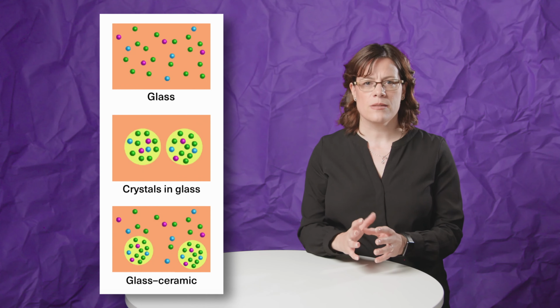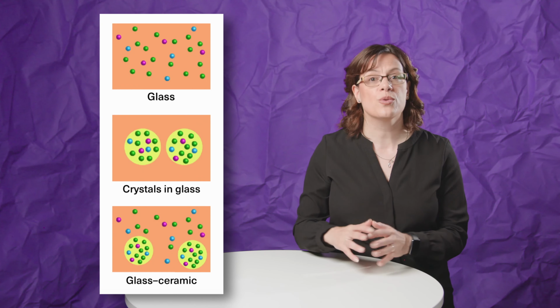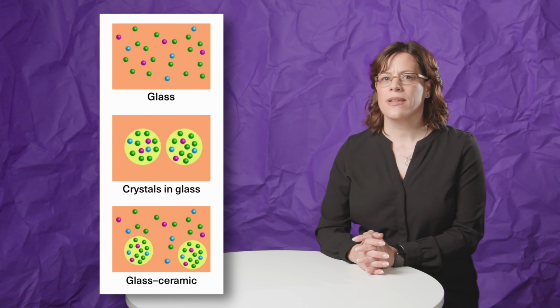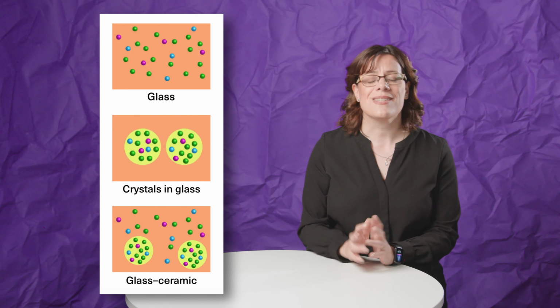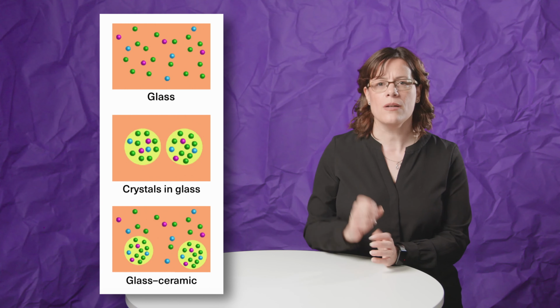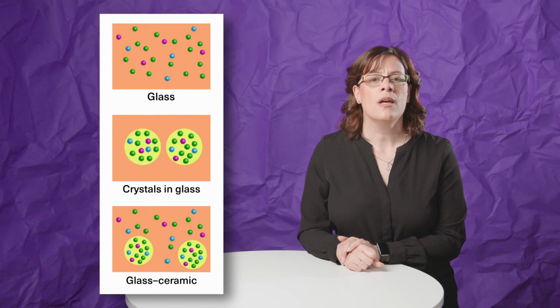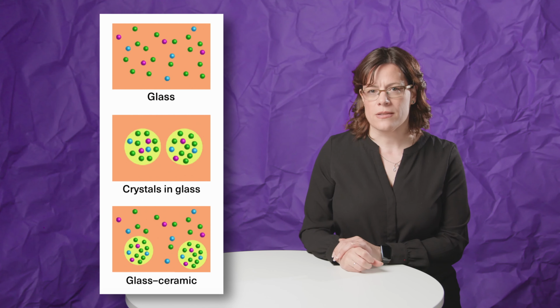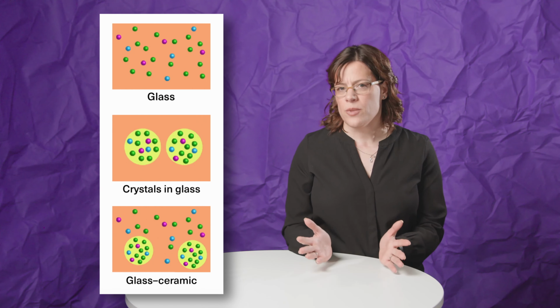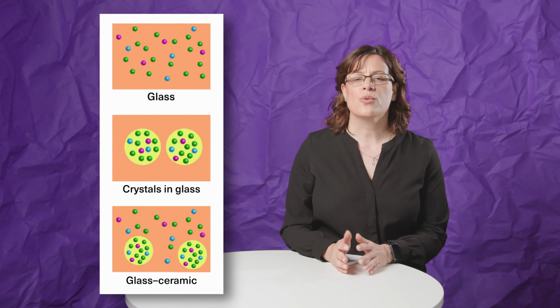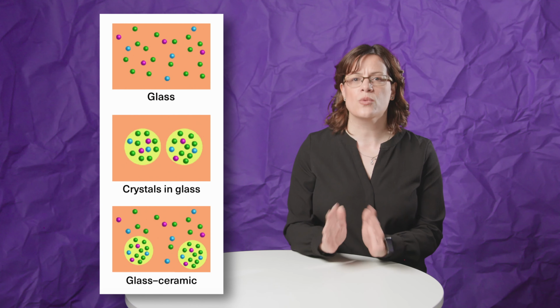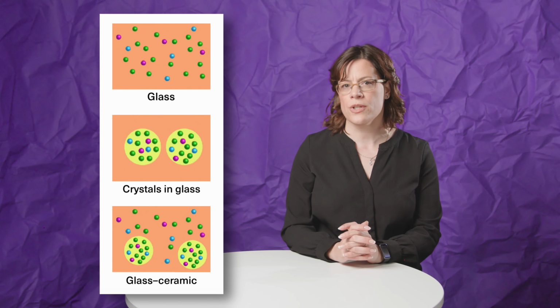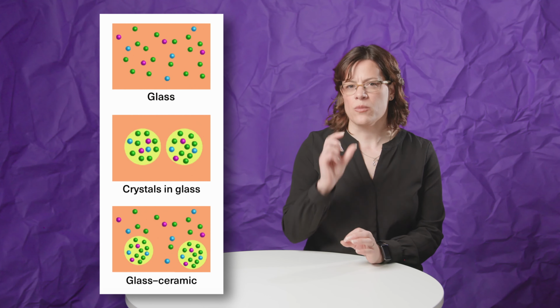Another research activity is focused on the development of glass ceramics. Glass ceramics are glasses which are heat-treated in order to grow crystals. This glass ceramic can exhibit better performances than glasses if the rare earth ions are located in crystal with specific crystalline phase. To be promising for photonics application, the crystals should also grow in the volume of the glass, and their growth should also be controlled, so transparent glass ceramic with small-sized crystal can be prepared.